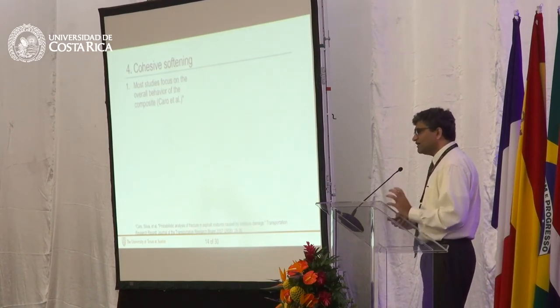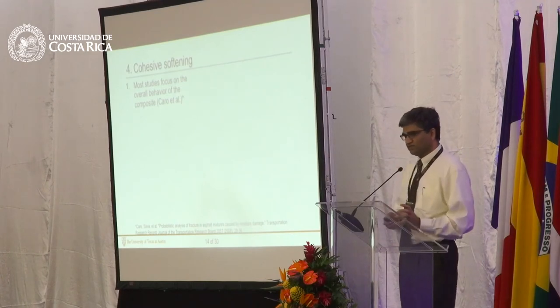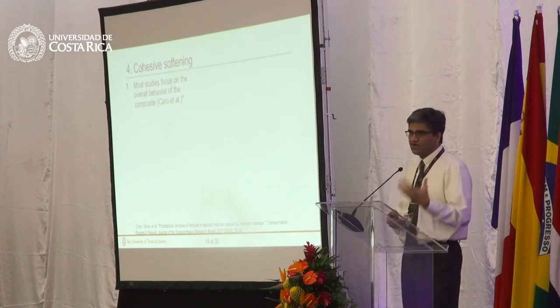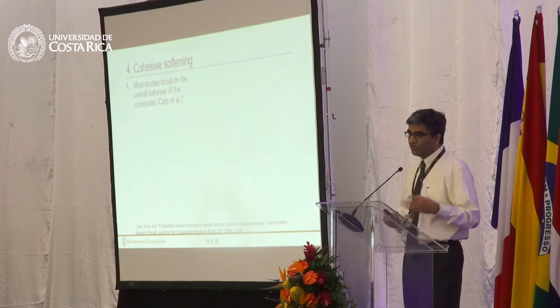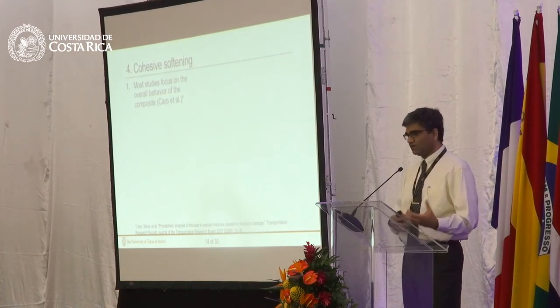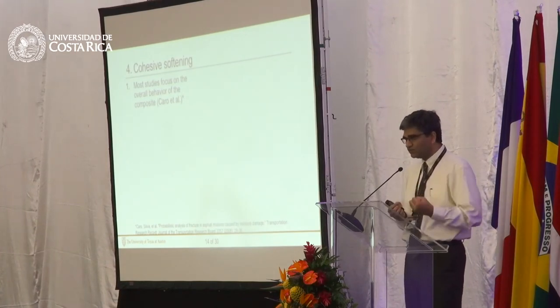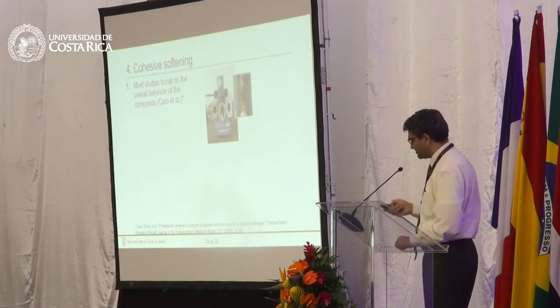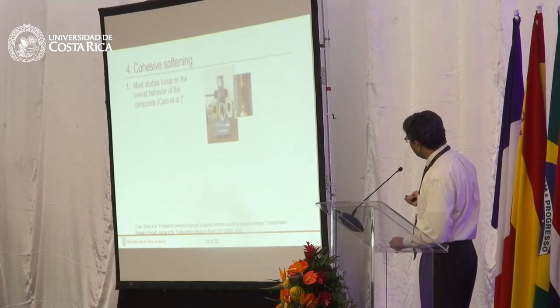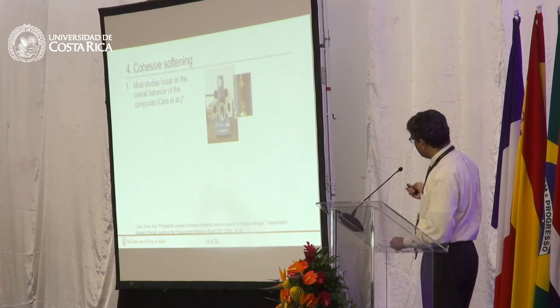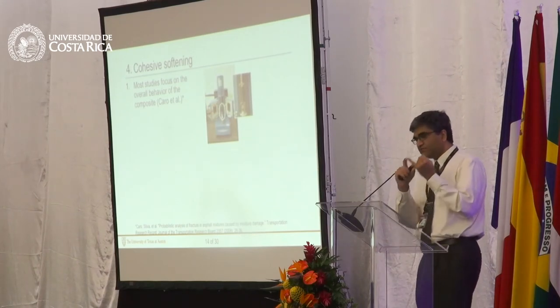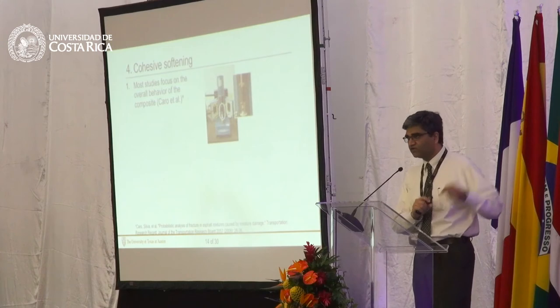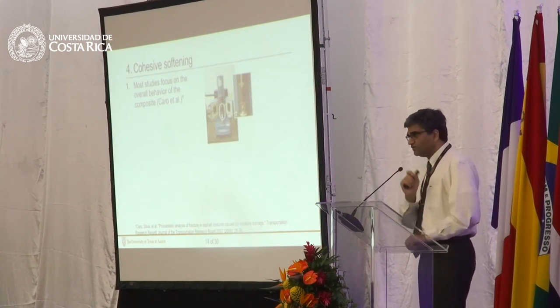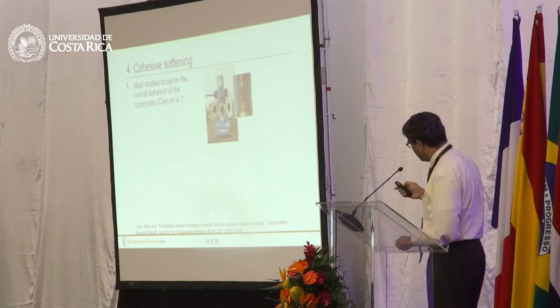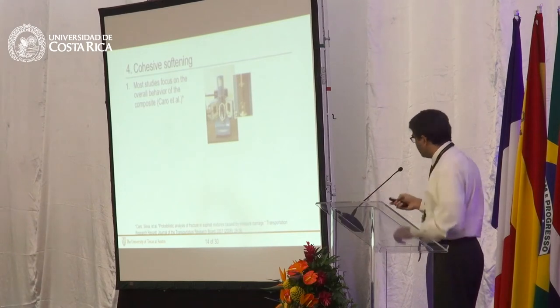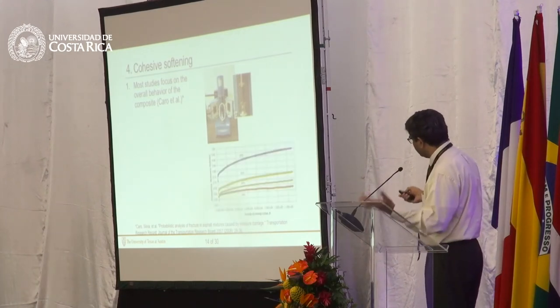Now, this is where it gets a little tricky. If you use composites for moisture damage, you have to understand and recognize that all of these mechanisms are occurring together, and so you have to tease out the parameters of interest. But it was an interesting study. This study also used a DMA specimen, a mortar specimen, the same specimen that you'd seen submerged before in water, that same tiny little specimen with asphalt binder and the fine aggregates that come from the mix, and you could construct fatigue damage curves.